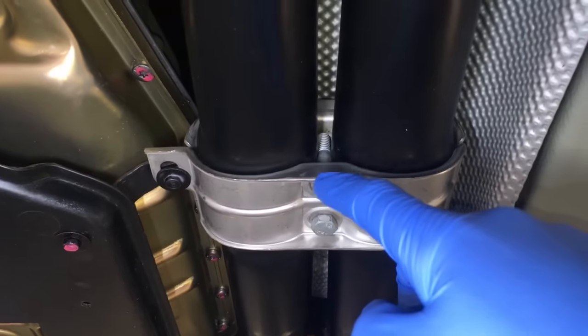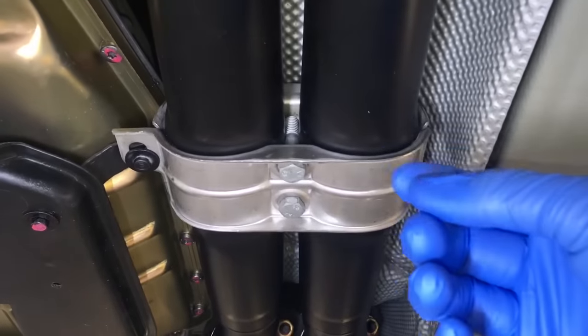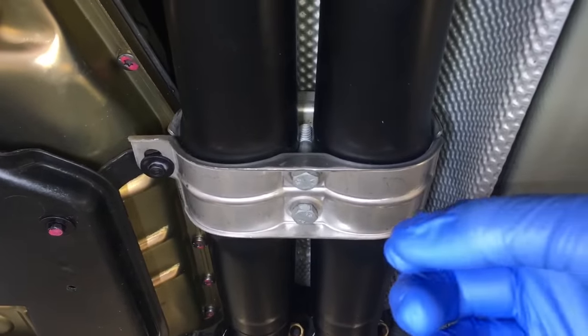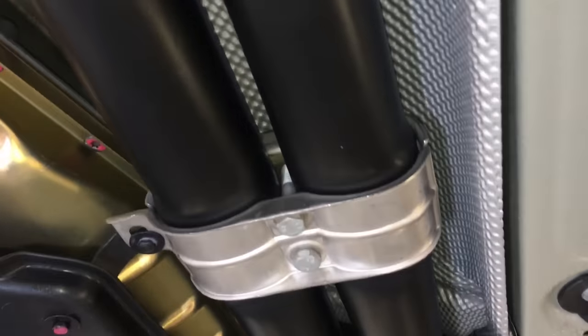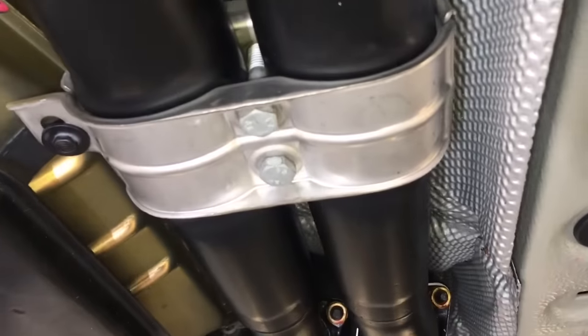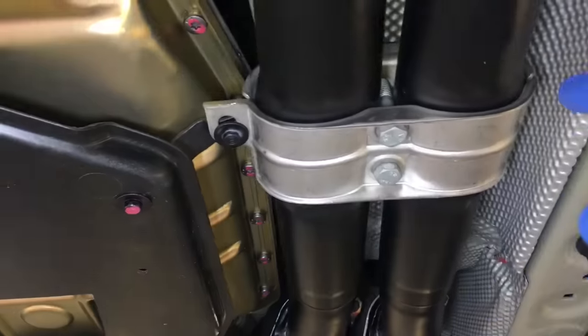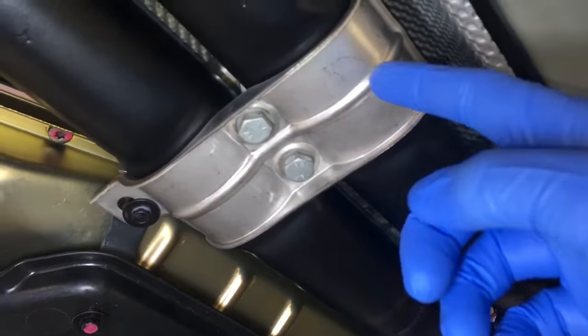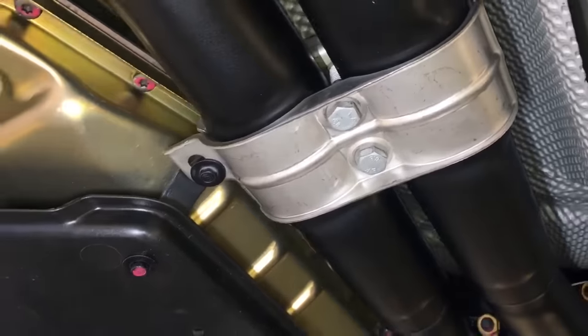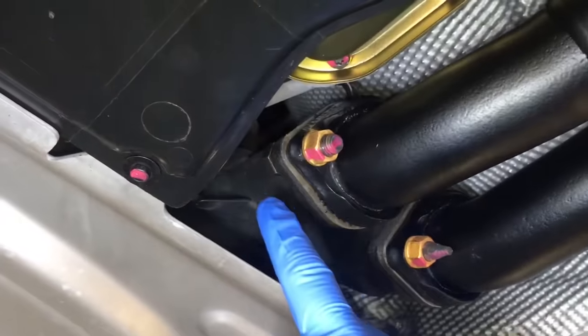Normally these bolts, and specifically on these ones, were completely rotted away to a point where the inside of those pipes were completely thin and basically snapped, because this corrosion had eaten into the steel of that M8 bolt, both of them, and they weren't doing anything anymore. They were just simply floating and could have slipped back, but corrosion had held that tight to the pipe. So once we'd powder coated the exhaust system, we put a new bracket system on that location up there. The exhaust downpipe had to have one new BMW bolt.